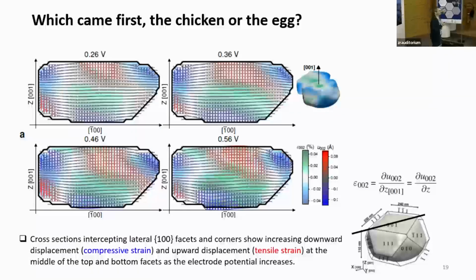Then there was a question for several months: which came first, the chicken or the egg? Is it that we have expansion of the top and bottom facet because of the preferential adsorption of anions at the edges and corners? Or do we have preferential adsorption of anions in this region, and that causes the compression of the edges and corners? Well, I think a good answer to this question came from this cross-section here, where we first cross a corner atom, then we cross the top facet, and then again one edge atom. What you may see is that there is an increasing inward displacement of these edge and corner atoms, and this leads to increasing strain distribution heterogeneity and expansion of these atoms here.